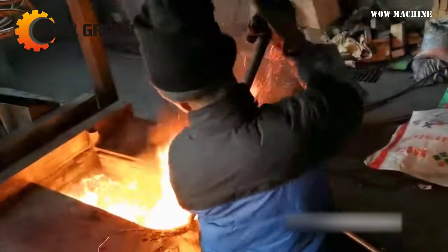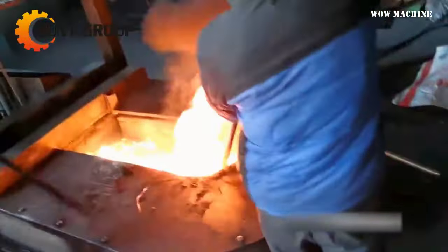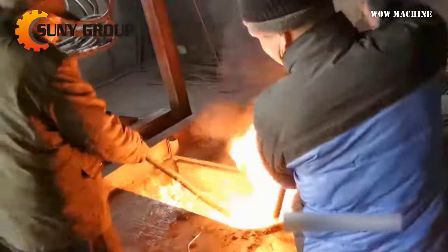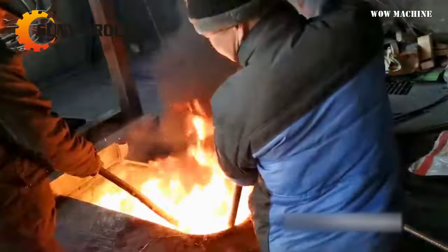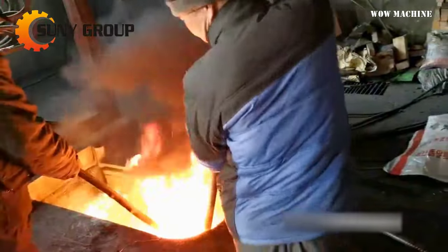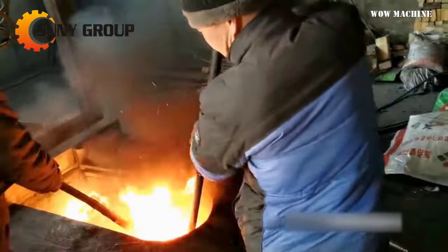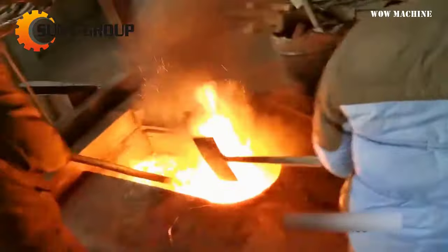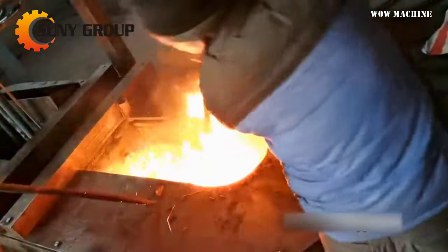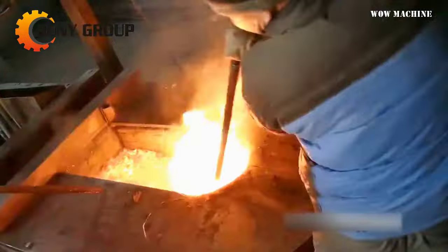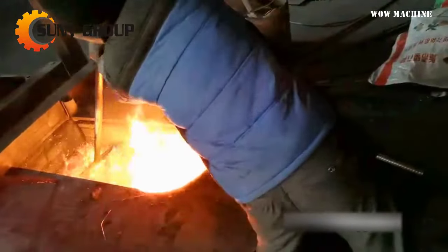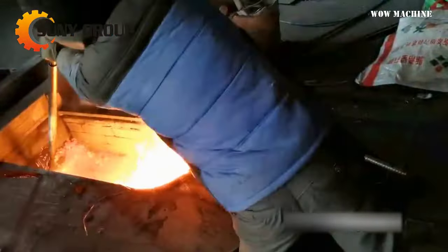Melting. The production process begins with the collection and preparation of Millberry copper wire scrap, a highly sought-after material due to its high copper content, usually around 99.9% purity, and minimal impurities. The scrap is first cleaned to remove any contaminants that could affect the melting process. Once cleaned, the copper scrap is loaded into a furnace for melting.